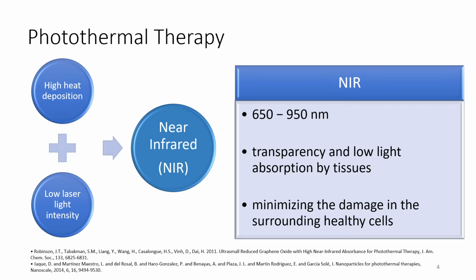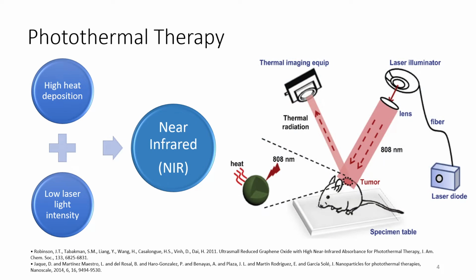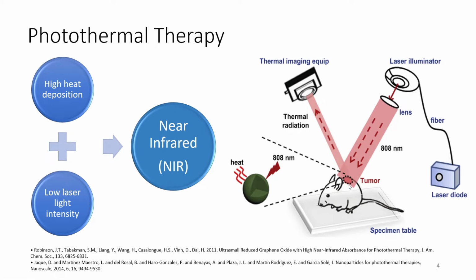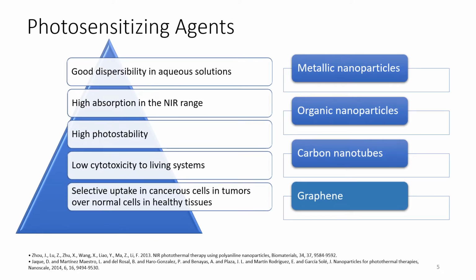irradiation. Its wavelength is in between 650 and 950 nanometers, and in this wavelength there is low light absorption by tissues, and this minimizes the damage in the surrounding healthy cells. So what we need is a laser illuminator and a photosensitizing agent at the tumor site. So photosensitizing agents should have good dispersibility, high absorption in the near infrared range, high photostability, low cytotoxicity to living system, and selective uptake in cancerous cells in tumors over normal cells in healthy tissues.